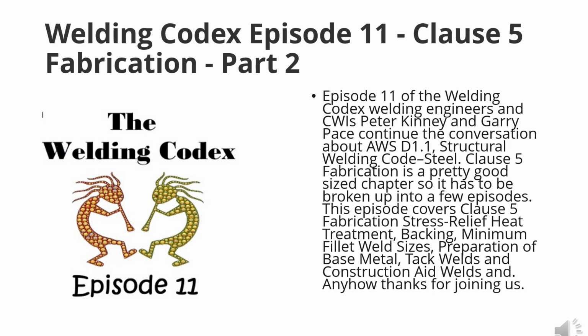Cyclically loaded, things change once things go from static to cyclic, and sometimes you may have to remove your backing as opposed to leaving it in place. That's because on both sides of the root of where you tie into your backing, you have a perfect notch that's formed there. That's why on cyclically loaded structures you may have to remove it. And that's subject to what should be on the drawings as specified by the engineer or in the specifications associated with the project. Right, and it gives you a couple of examples there, some wording on do this, don't do that, that you can read through and figure out on backing welds.